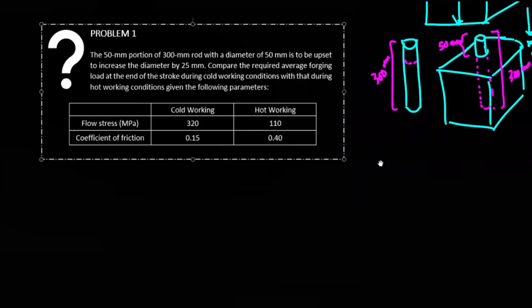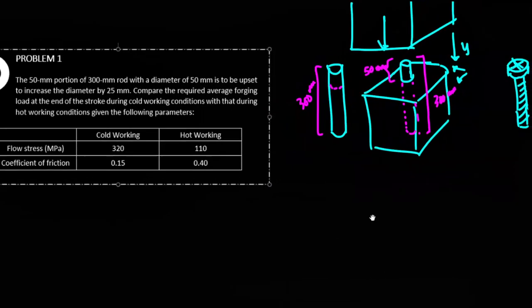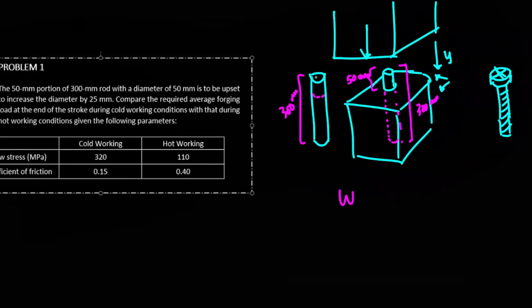First is assess muna natin, although it's obvious, no? Usually cylinders, when we are forging it across its circular cross-sectional area, this usually means na homogeneous deformation siya. Okay? So homogeneous siya because if you compute it, yung width niya, since it's circular, equal siya. So if you look at this direction, this is the width. And if you look at this direction, this is the bite. Or pwede rin opposite, no? But in any case, yung width niya and your bite niya is just equal, no? Width is equal to bite. And therefore,